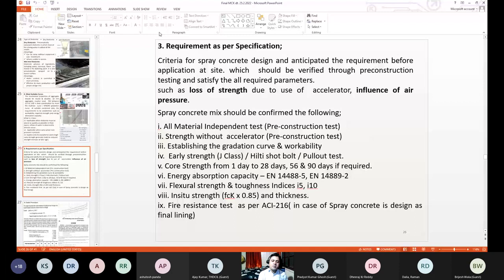Early strength can be done because it is done by the penetrometer, but for the Hilti shot bolt and pull-out test, the equipment is not available with the manufacturer. Depending upon the request, they may supply it. Core strength from 1 day to 28 days should be confirmed. The energy absorption capacity as per the EN should be confirmed. The flexural strength and toughness indices I5, I10 shall be checked.